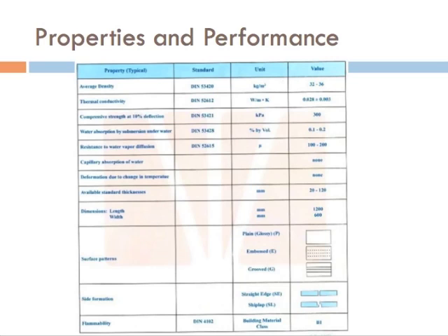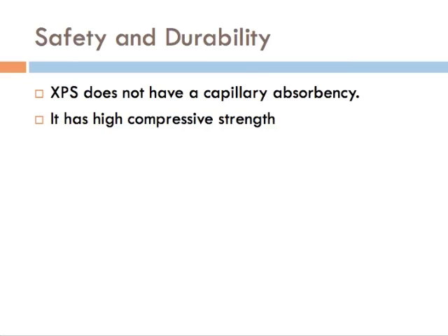0.028 watts per meter Kelvin. The compressive strength is quite high. It's 300 kilopascals and has a very low water absorption. It's not flammable, and the available dimensions are in the table. It can come as plain, glossy, or embossed or grooved, and it is resistant to water vapor diffusion. However, it does not have a capillary absorbency, but it has a high compressive strength.